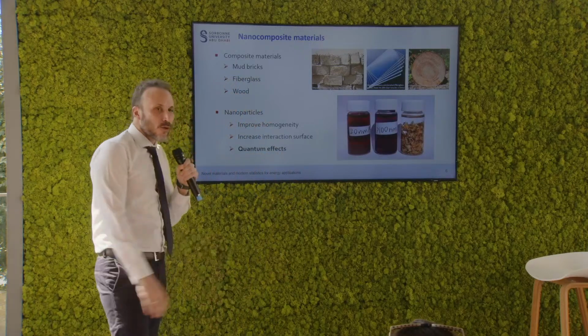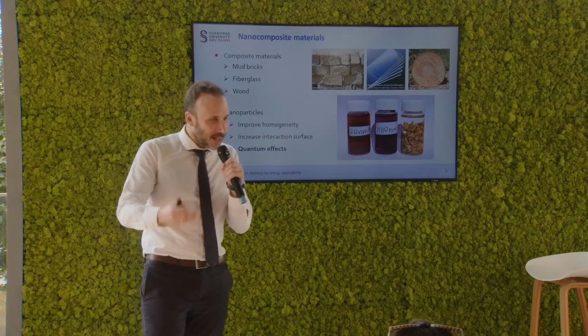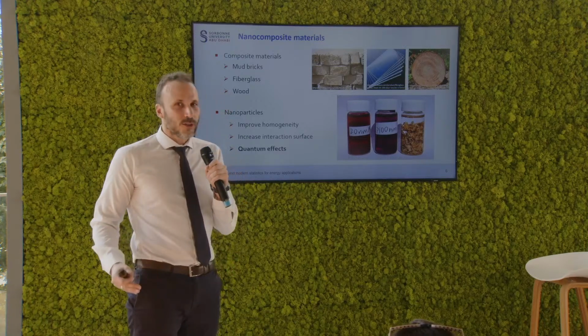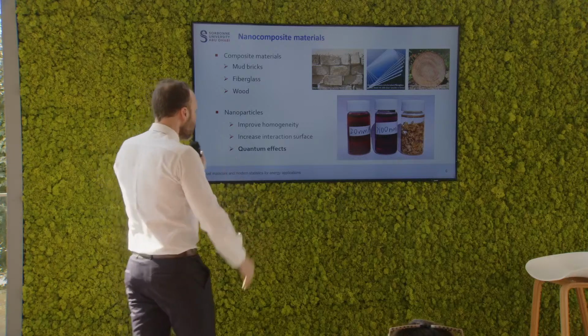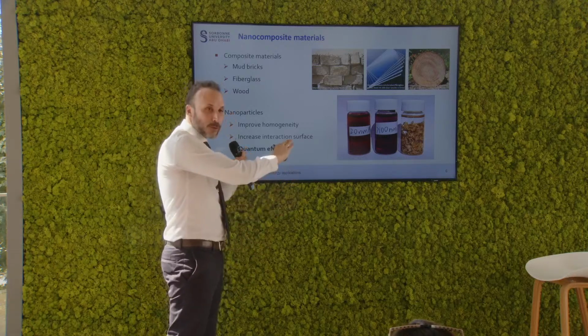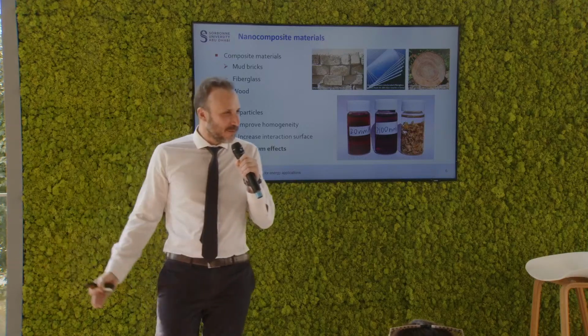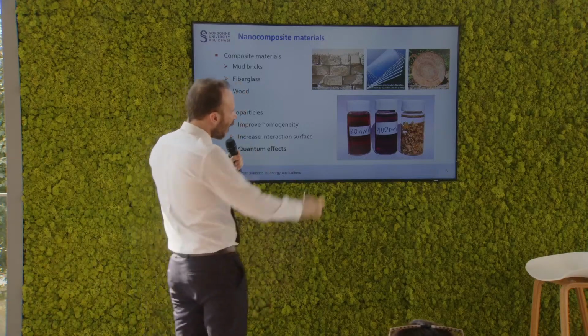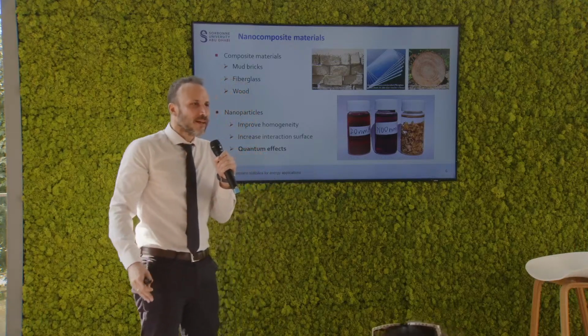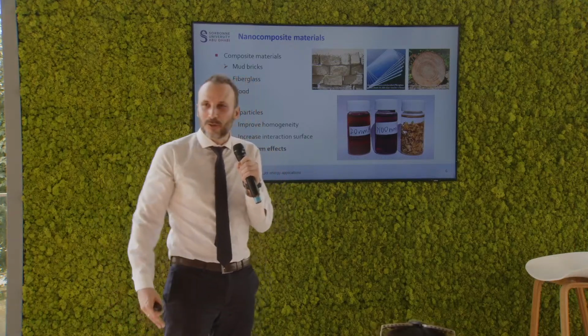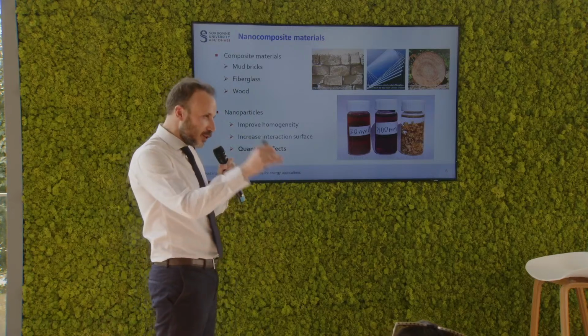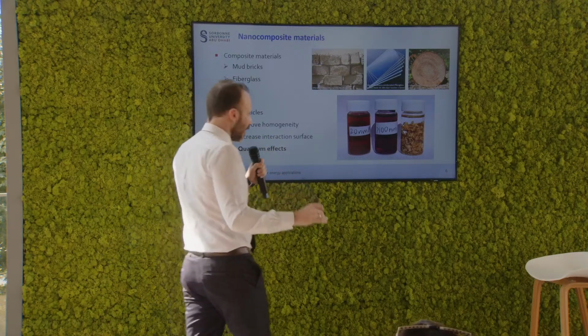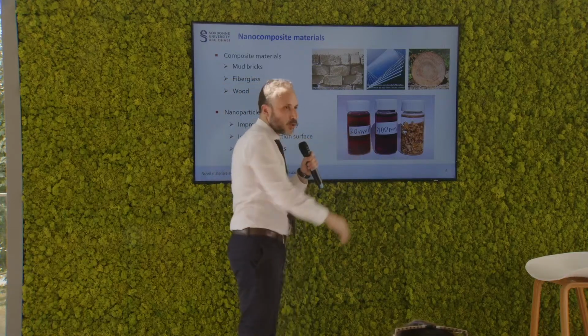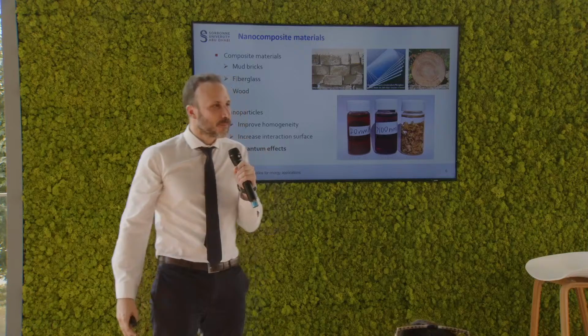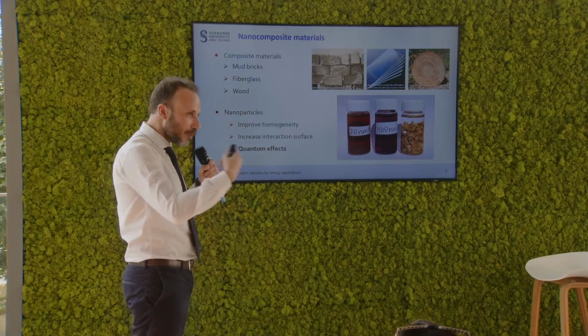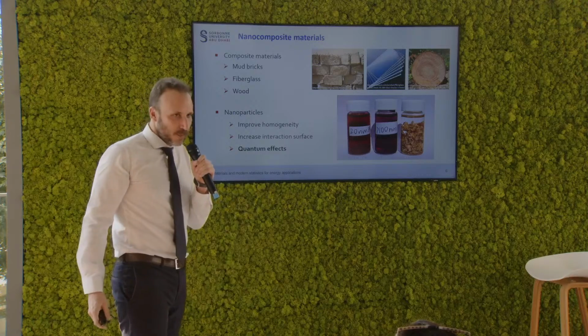Finally, thanks to their extremely small size, their nanoscale size, nanoparticles can give birth to exotic phenomena, which are quantum effects. In a very random example, the vial on the right hosts big gold particles, which we are all familiar with, the way they look. But if I reduce the size of the gold particles significantly to around 100 nanometers and even down to 20, the solution starts looking purple or even red. And that is based on the properties that are given birth to through the nanoparticles.